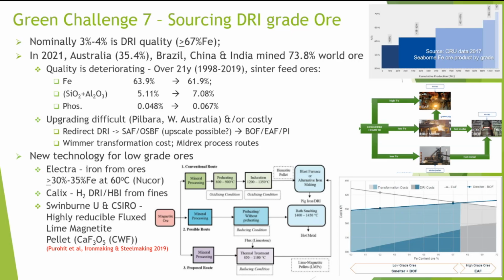We're already seeing a 2% drop in iron content. Silica and alumina are increasing by 2%, and the phosphorus increased by about 0.02%. 35% of the ore comes from Australia, and the Pilbara ores that they have there are difficult and costly to upgrade. They're doing a lot of work on it.